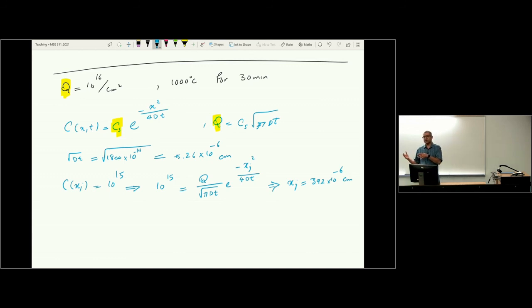With the first one, it's easy. We just have a flow of gas of the dopants, and they keep bringing new dopants to the surface. And with that method, we can get any doping level at any depth, theoretically. In most cases, we really do not go beyond maybe a micrometer in depth for doping levels on the order of 10 to the 15, 16.